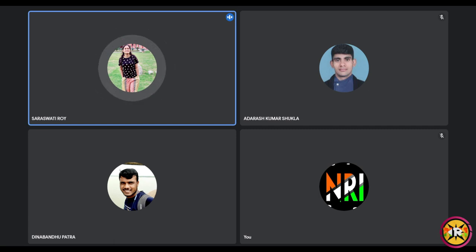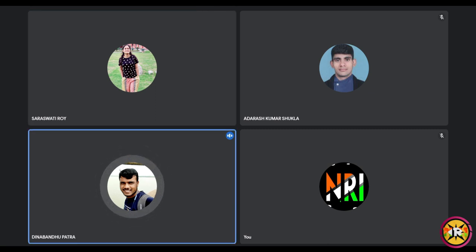So are you saying about the last XPS? The first XPS I'm talking about. Or should I open that? Just a minute. No, I mean in the as-synthesized sample you have fitted the oxygen XPS into three peaks, before doing the OER. Yes. So there you did not dip the sample in the alkaline solution, right? No, no. So if you dip the sample in the alkaline medium, like a blank reaction without any electrolysis, just dip the sample in alkaline medium, take it out, dry it and submit for XPS, you will not see the CoOOH peak, right?